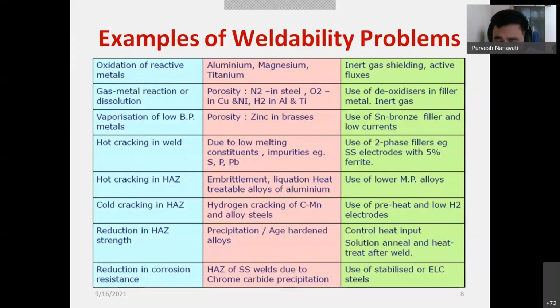Okay, now I have some examples of weldability problems. So oxidation of reactive metals, most of the time I have mentioned aluminum, magnesium, and titanium. You have to provide proper inert gas shielding and active fluxes. Then gas metal reaction or dissolution, most of the time when the weld pool is not protected. You have porosity due to nitrogen in steel and oxygen in copper and nickel, and due to hydrogen, you have porosity in aluminum and nickel based alloy.